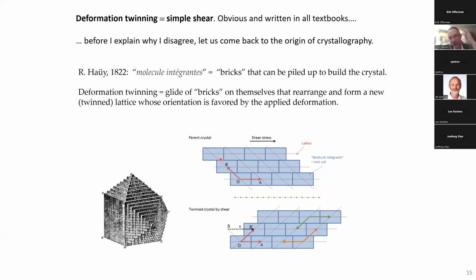So if you have this representation in mind, it's quite easy to imagine what deformation twinning could be. For example, if we take this crystal made of bricks, where the motif is a brick, we glide the bricks along this direction, and for a certain amount of shear, of displacement of the bricks, we can restore the lattice here. Look, this lattice here is in mirror symmetry with this lattice here. It means that we have restored the lattice. It's very compatible with shearing, it's really natural if you imagine this motif as bricks.